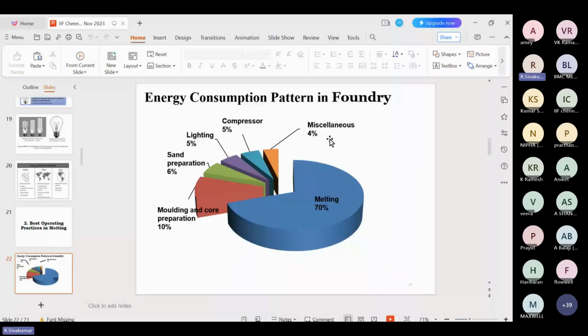Okay, this is the energy consumption pattern in a foundry. It is taken for only induction furnace based foundry. Typically, in any induction furnace based foundry unit, the majority of the energy is spent in the melting section, almost 70%. But from foundry to foundry it varies from 65 to 75%. Some units are using 80% also.